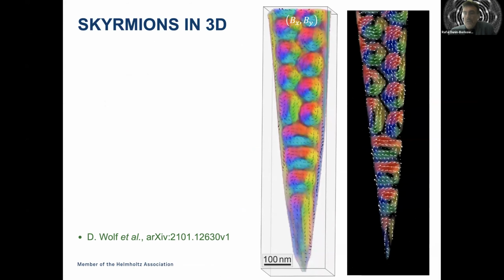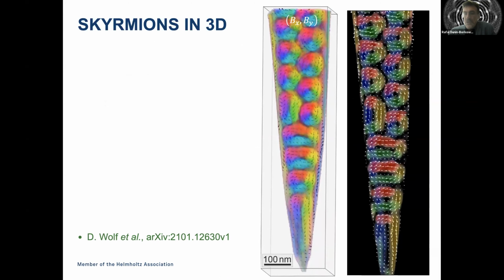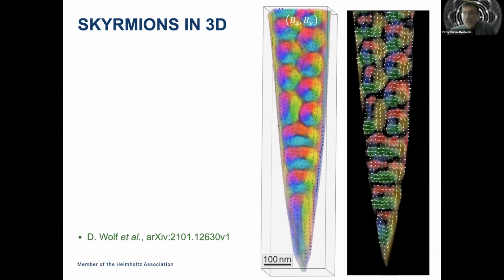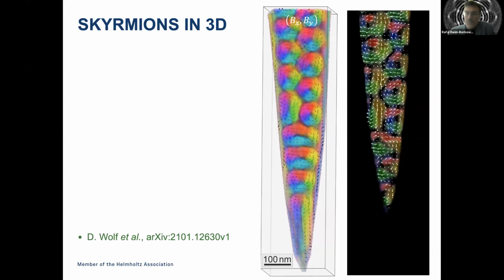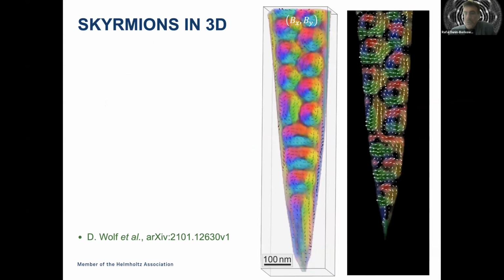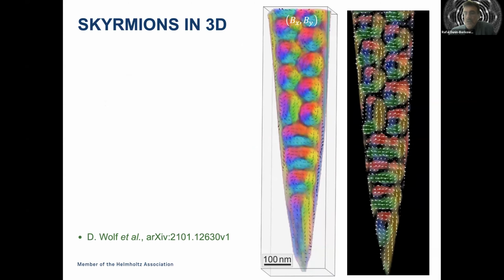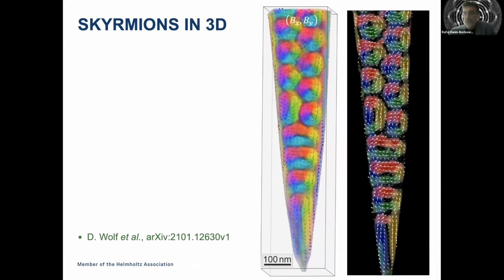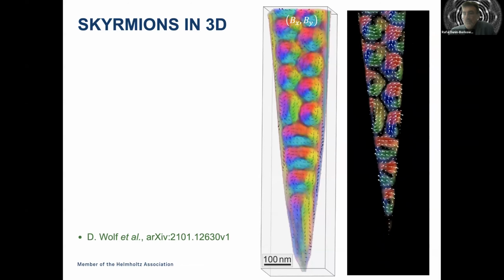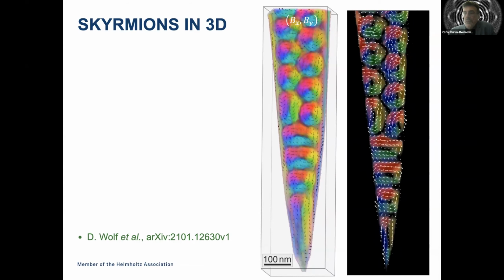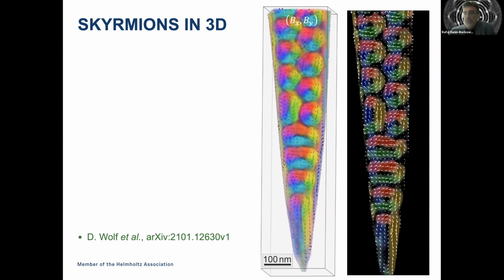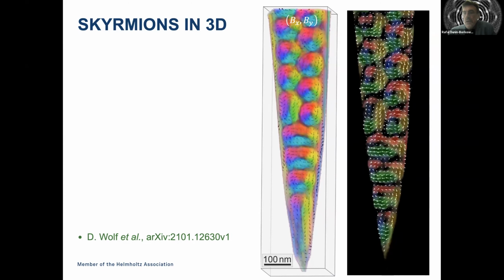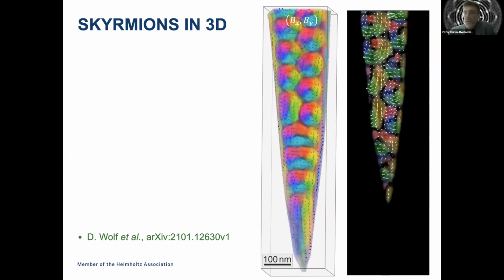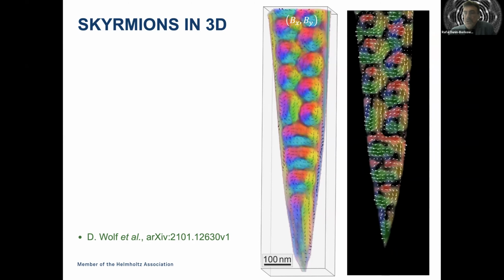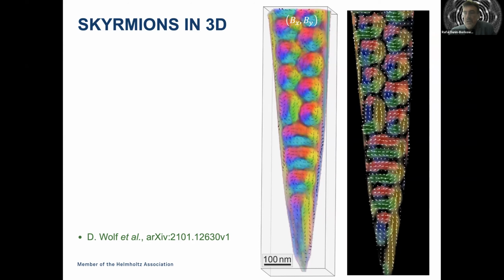And I'll play a little movie here, which shows slices of the 3-dimensional distribution of Bx and By inside the sample, imaged as a function of distance Z through the needle. And you may just be able to see that the centers of some of the skyrmions change in position from slice to slice.